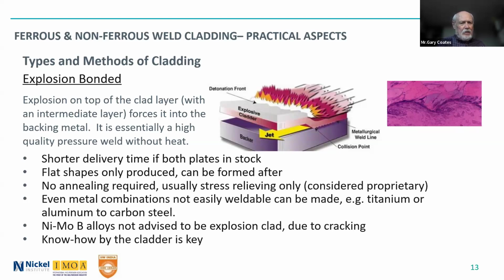Another good advantage is the metal combinations that are not easily weldable can be made. For example, titanium and aluminum can be bonded with carbon steel, and the pot that we looked at in the very beginning slides, that is done by explosive cladding. There are a few alloys that you don't want to explosion clad. The nickel molybdenum Hastelloy B type alloys, they tend to crack because of the high stresses involved.